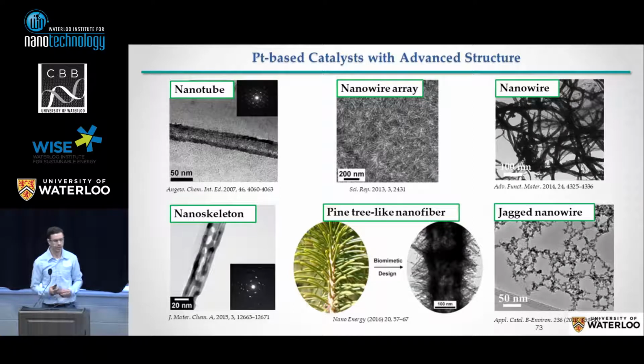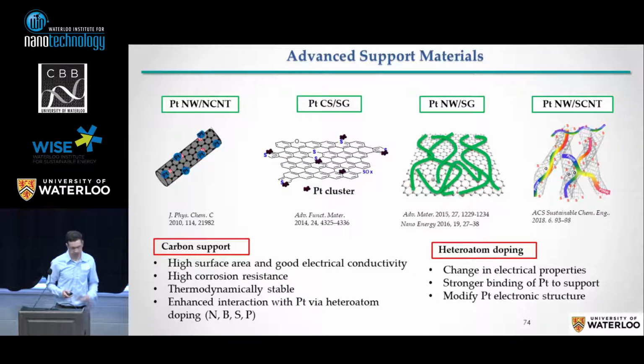And also, besides the platinum itself, another strategy is to tinker with the support for the platinum. So this lets you more evenly disperse the platinum and also lets you maintain the stability of the platinum as well to avoid it agglomerating, forming larger particles, which will then cause wasted platinum to be inside. Okay, so then there's more work as well on advanced support materials. Again, if anyone's curious about these things, feel free to talk to me afterwards, and I can put you in touch with the people working on these specific things.